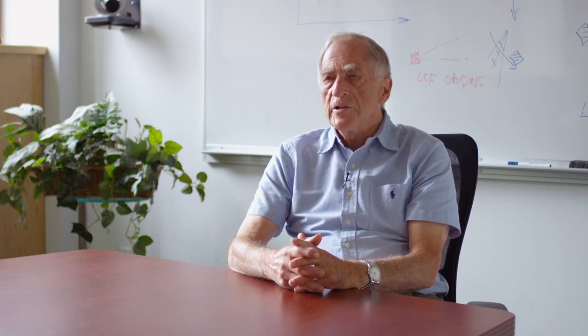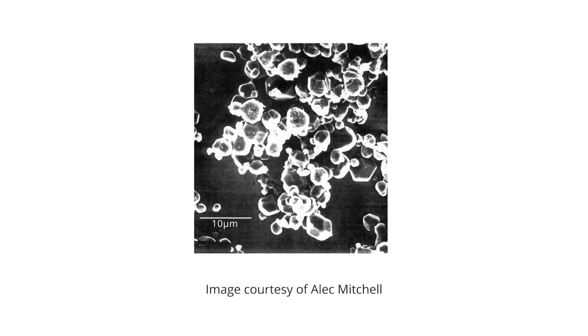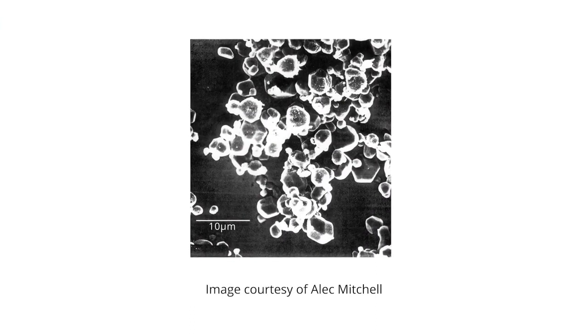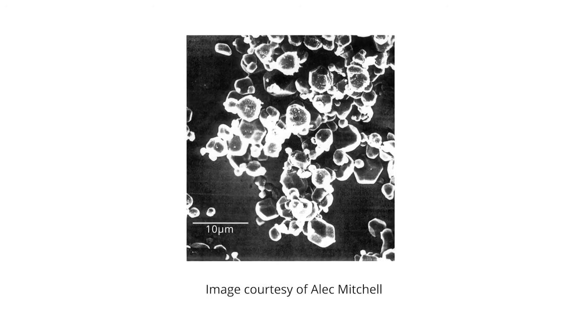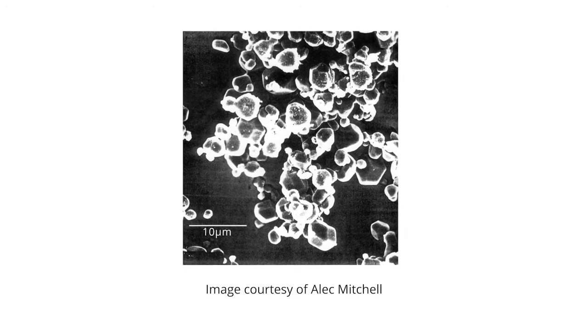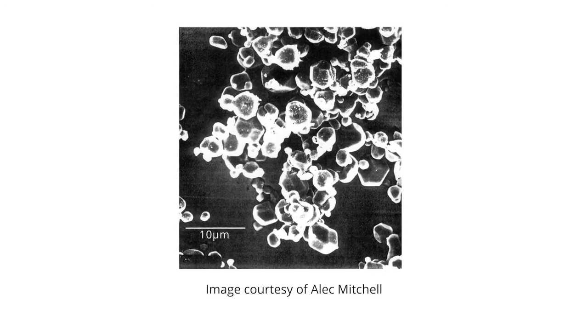The first thing that we did was to look more closely at exactly what were the inclusions that were being found on the fracture origins. And we found basically three factors were involved. The first factor was the presence of oxide inclusions, which are inevitable in the superalloys. And we found that they were being glued together by titanium nitrides. So if we looked at the inclusion collections in 3 dimensions, we found oxide particles which were stuck together in a 3-dimensional network by titanium nitrides.